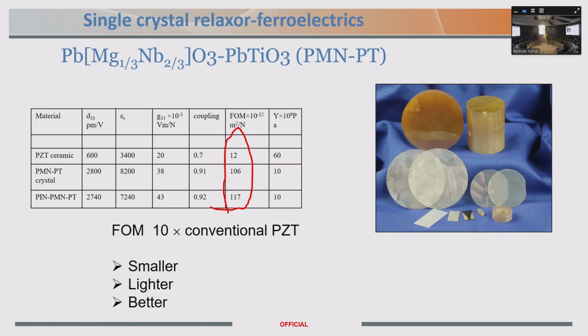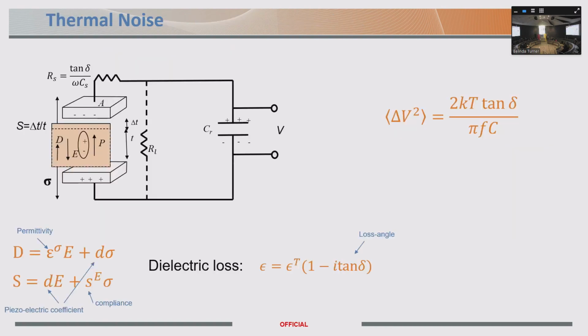And the reason is because sensitivity is not so much about how much energy you can extract from the field, it's about how much information you can extract from the field. And in order to understand how much information you can extract, you need to understand what the noise is, what's the minimal amount of energy, if you like, that you can extract from the field. So it turns out that when you rotate these polarization vectors inside the material, you generate a little bit of heat. There's friction, right? And because it's a thermal effect, whenever you have friction, you have what are called thermodynamic fluctuations, and those fluctuations cause voltage fluctuations even when there's no pressure acting on the sensor. And so those voltage fluctuations set a limit on the minimum voltage that can be measured.